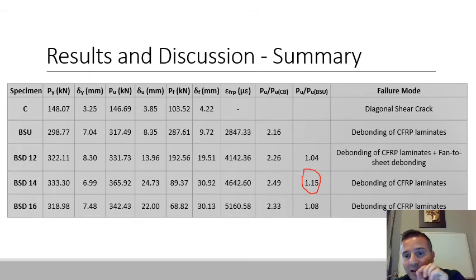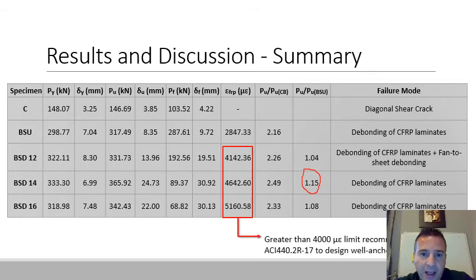Our aim is not only the strength and the ductility. The ductility was increased significantly, and the strains, according to the code shear design provisions, the ACI, won't allow you to exceed 0.004, which is around 4,000 microstrain. You can see here that all three sheets, the anchored ones with the dowels, exceeded the 4,000, and the one with the 16 even reached 5,000. So basically we are utilizing more of the strength of the material, and we are able to reach the limit of 0.004, which is related to the aggregate interlock in shear.